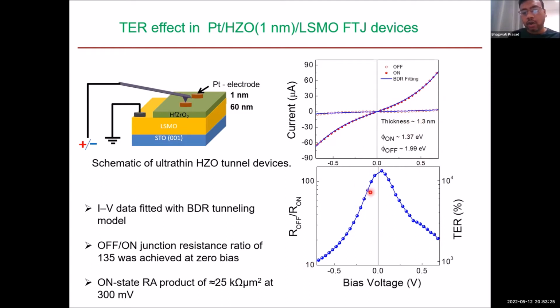This is the on to off ratio of the device with the bias voltage. We see that the on to off ratio decreases when you increase the bias voltage. In fact, around 300 millivolts, which gives a good enough current for the read, you still see a significant on to off ratio. The corresponding RA product that we see is around 25 kilo ohm micrometer squared, which is around 3 orders of magnitude smaller than what people have seen.